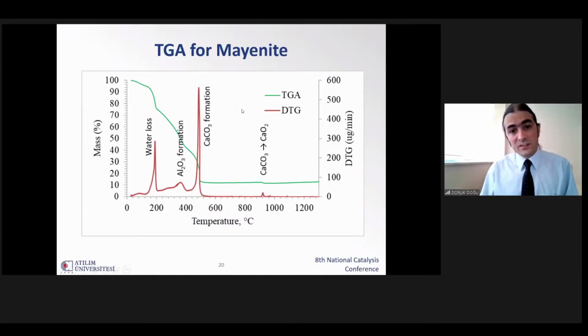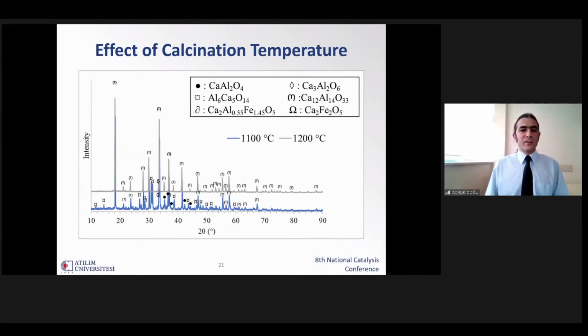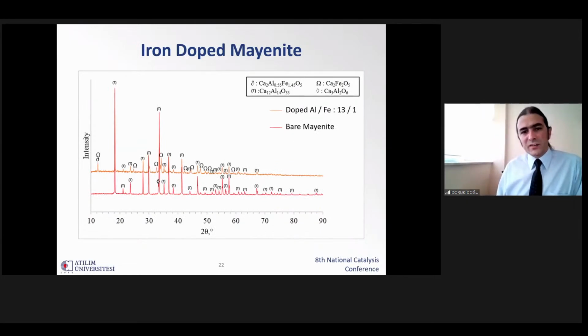From this TGA, we can see that it has to be definitely above 950, but at those temperatures, we couldn't get homogeneous, nice mayenite structures. We need at least 1100 degrees Celsius to get some good mayenite structure. And as you can see, at 1100, we still have some impurity phases. At 1200, we were able to get rid of these impurities and get pure mayenite structure. Also, we tried introducing iron in the structure because we think that by introducing iron, we might improve its catalytic activity.